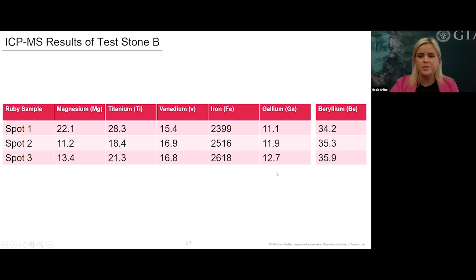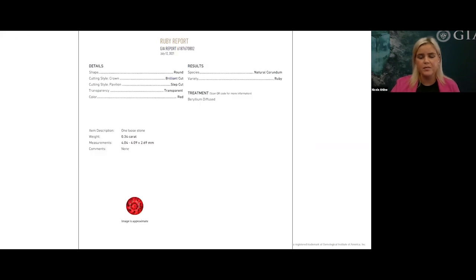Those beryllium levels are very high. With that high temperature heat treatment, the levels are so high that this ruby will go out as beryllium diffused. Now, when a ruby or sapphire is titanium or beryllium diffused, it does not qualify anymore for an origin report. So this report will not be transferred over to an origin report, and you see that at the top, it doesn't say ruby origin report. It will just say ruby report. It goes out as a natural corundum ruby, and we completely remove any comment about the geographic origin. Again, the treatment will be beryllium diffused.